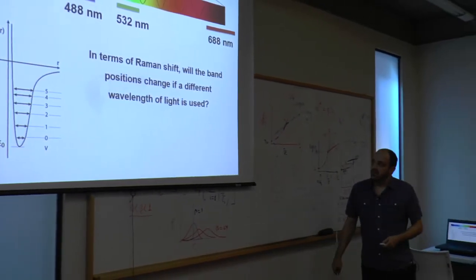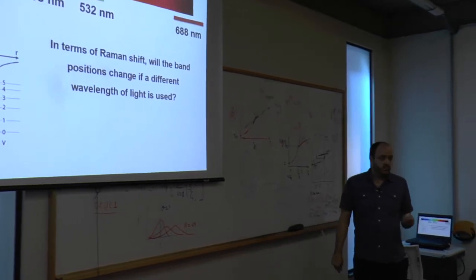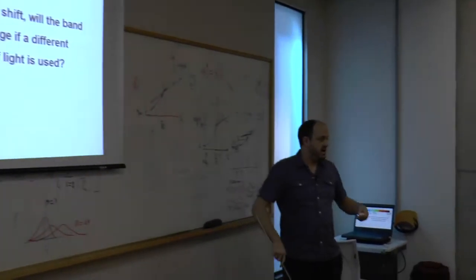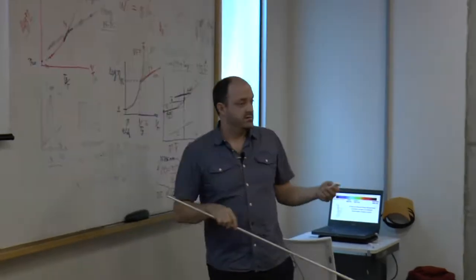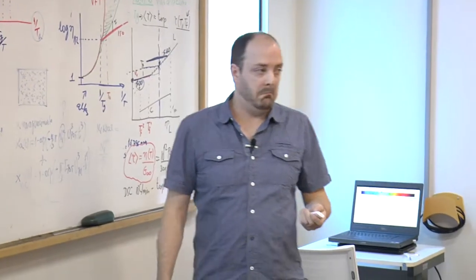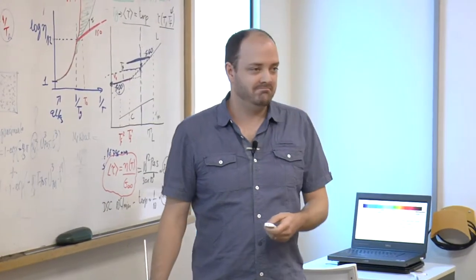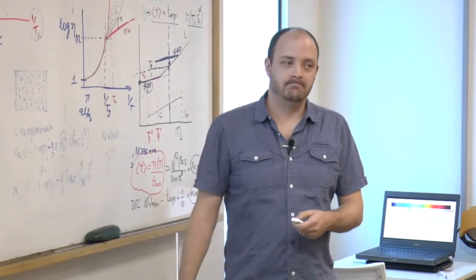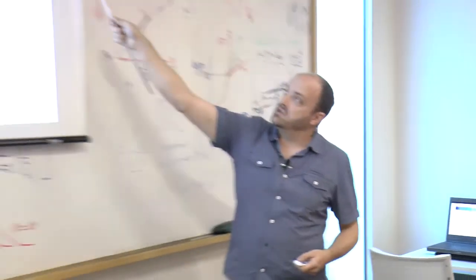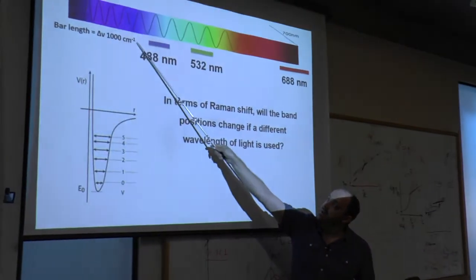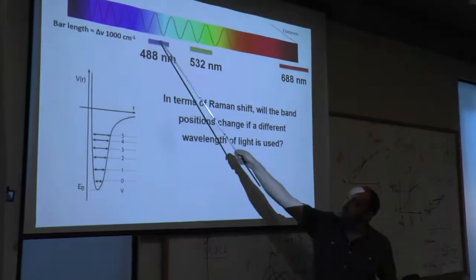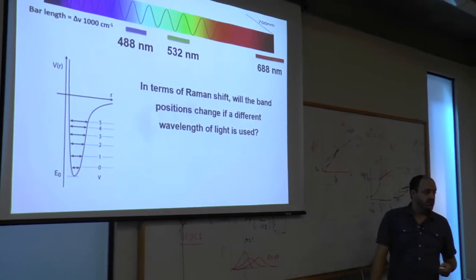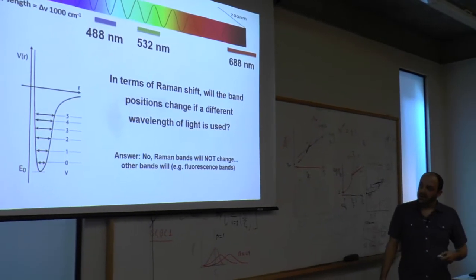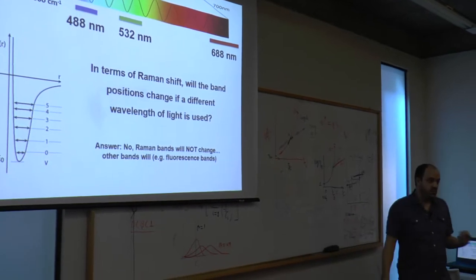So, do any of you have a guess? In terms of Raman shift, will the band positions change if we actually use different excitation wavelengths? Any guesses? Because we have a much longer scale for the same 1,000 wave numbers. In the spectrum, it's a smaller wavelength here and a longer wavelength there. And the answer is that the Raman bands won't change.